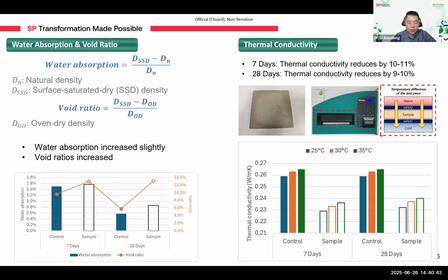The water absorption was calculated as the difference between the surface saturated dry density and the natural density, divided by the natural density. And similarly, the void ratio was determined by the difference between the surface saturated dry density and the oven dry density, divided by the oven dry density.